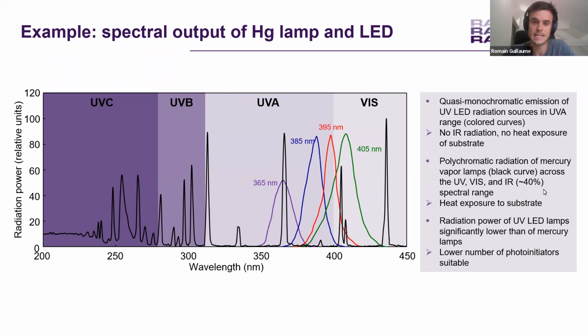So if we start with the LEDs itself, we have an almost monochromatic emission of UVA. So you have, for example, the purple curve, which is the emission of a 365 nanometers LED. On the market, we have also very often 385 nanometers or 395 nanometers or 405 nanometers wavelengths. So we can see that compared to the broad spectrum of mercury lamp, which is represented by the black curve, we don't have the same amount of photons. We don't have the same distribution of photons.